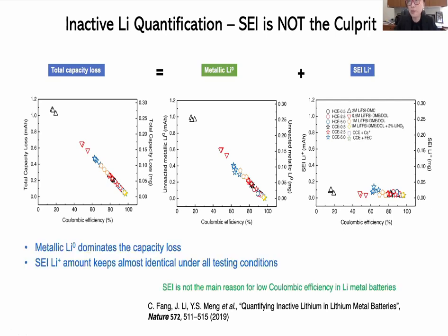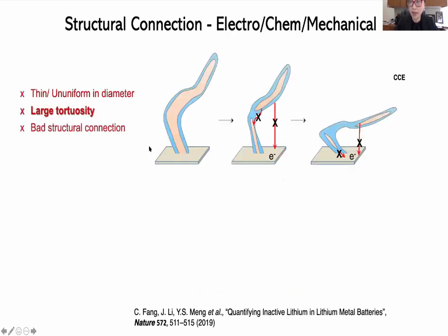So this discovery from a couple of years ago is so important to realize the low efficiency is mostly caused by the contact loss of lithium, right? If you have a very tortuous microstructure, you can actually run into the situation where the electric pathway is cut off. So those lithium become electrochemically inactive.